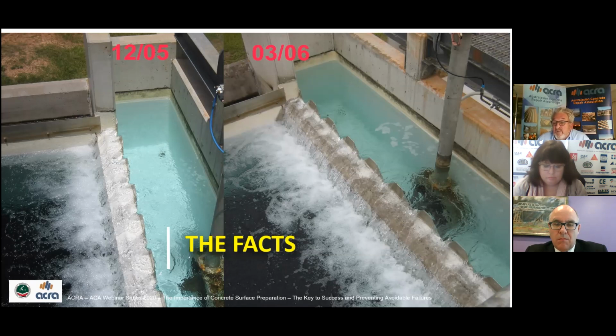We had inadequate product cure before recommissioning. That didn't help. Shutdown was required to remove defective coating and re-prepare and recoat to let it cure prior to recommissioning. It was 3 weeks all up, so it was costly to the client and costly to the contractor.